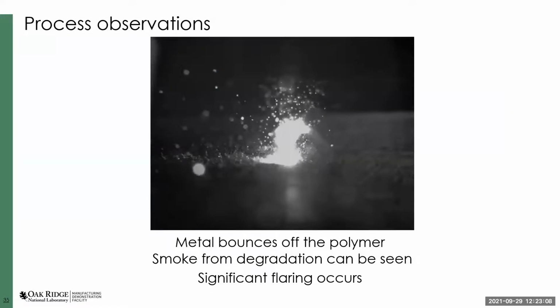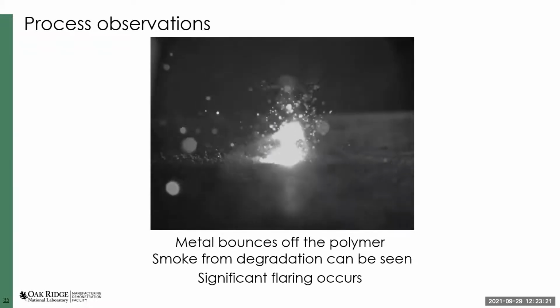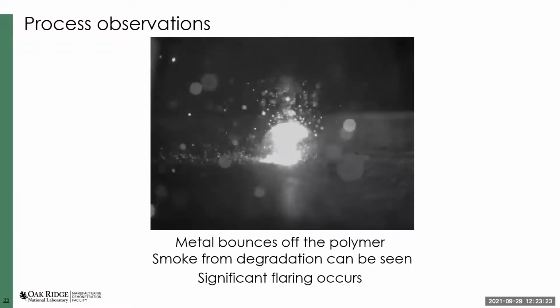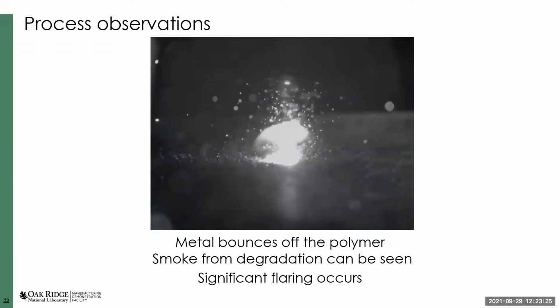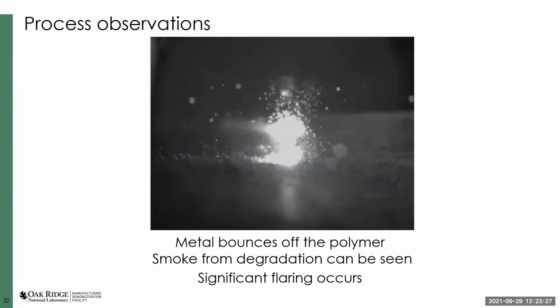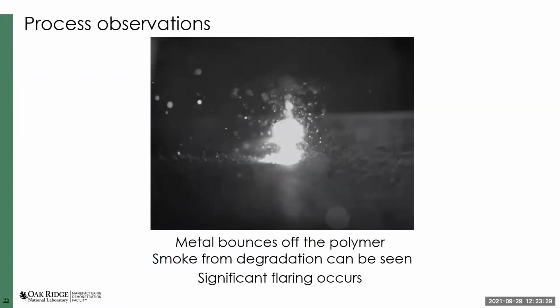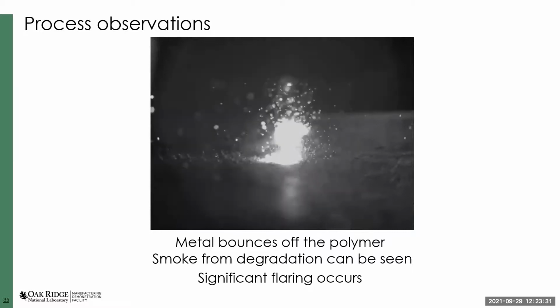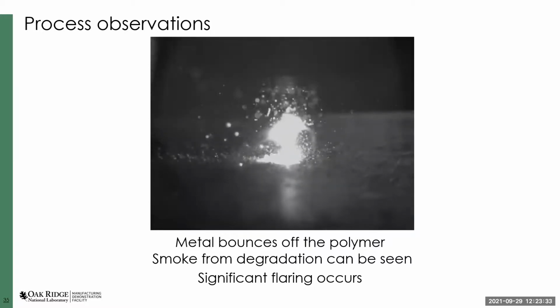Our next step was to set up some high-speed imaging to see if we can figure out what's happening in the process and confirm any of our hypotheses about what's going on. You can see in this video that we're definitely getting a lot of flaring at the point at which the laser is hitting the polymer. You can also see that the metal is not wetting the material very well.